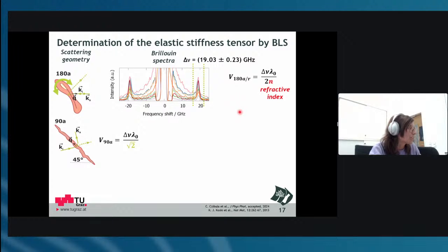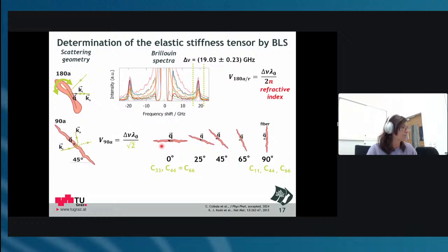One reason for that is, it has the drawback that it's very slow, but the nice thing is the refractive index falls out of the formula. So I just need to know my frequency shift and the laser wavelength to determine the sound velocity. For this whole stiffness tensor determination, we stayed in 90A geometry and just turned the fiber in this setup from 0 to 90 degrees. From the 0-degree measurement, you can directly determine C33, and C44 and C66 are the same in this one. At 90 degrees, when the fiber is vertically aligned, you get C11, C44, and ideally C66 when you can distinguish them.